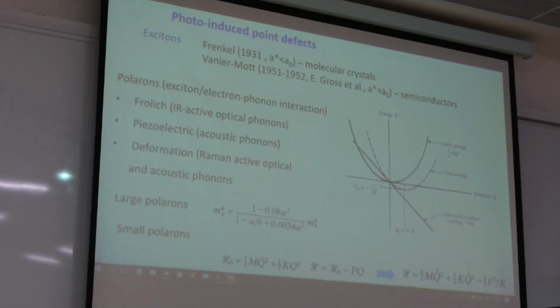And for Frenkel excitons, the distance between electron and hole is comparable to the atomic lattice crystallographic unit. So it's a very small particle which occupies some crystalline site. And there are much bigger excitons which have size over many nanometers. So the distance between electron and hole is very big, and it's called the Wannier-Mott exciton. This is typical for semiconductors, and you usually consider this kind of stuff, but to produce point defects, we are much more interested in the first one, which is untypical.